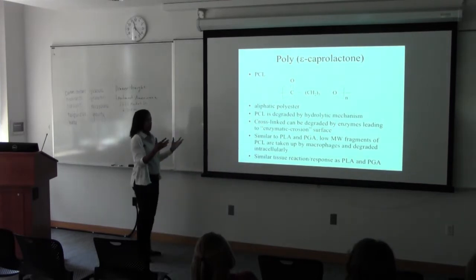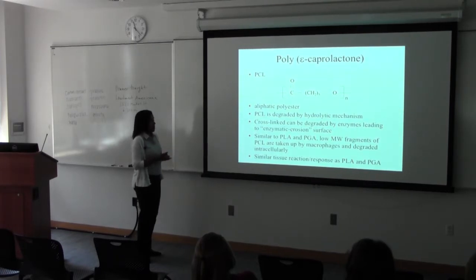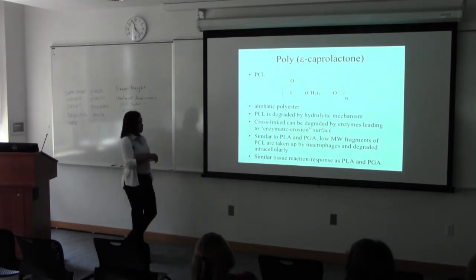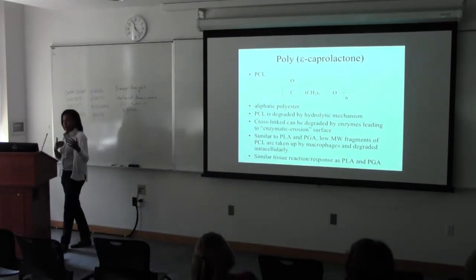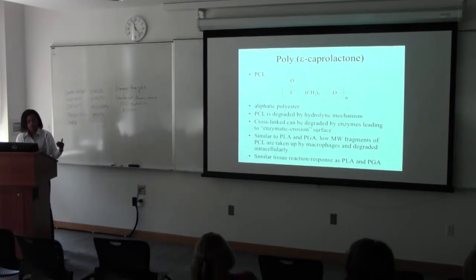It's very similar to the other ones, the PLGA and overall really PLA, and it's stable for a long period of time. This stuff will degrade over a period of 1 to 2 years. So if you want a stable polymer in your culture, this one's a good one. And you don't have that acidic byproduct breakdown happening in your culture. So that's a big plus with the polycaprolactone.